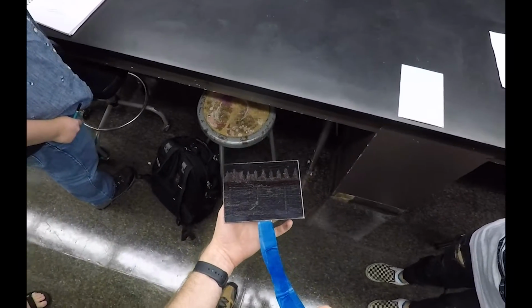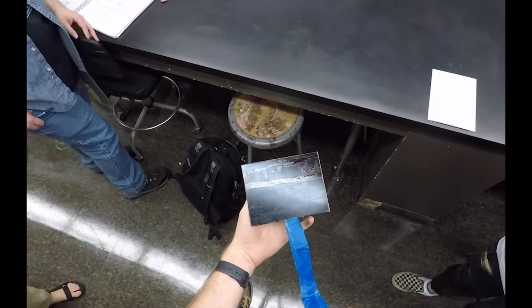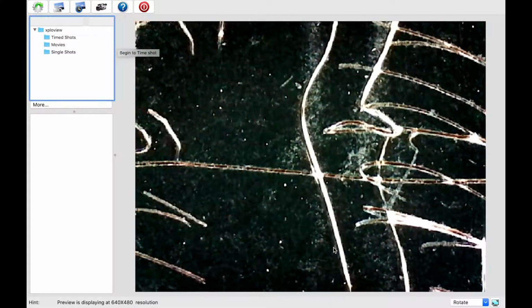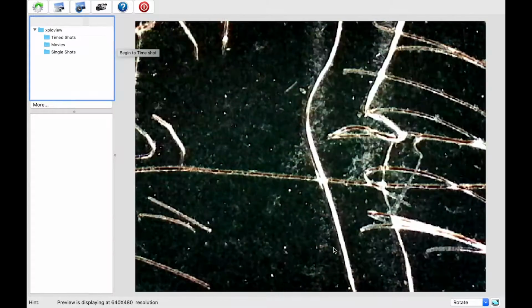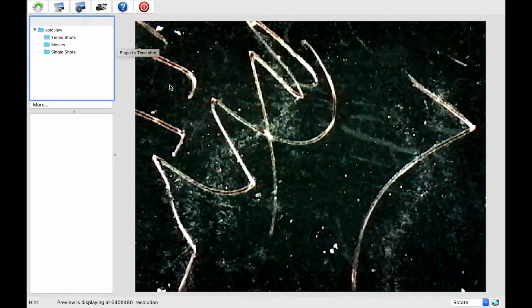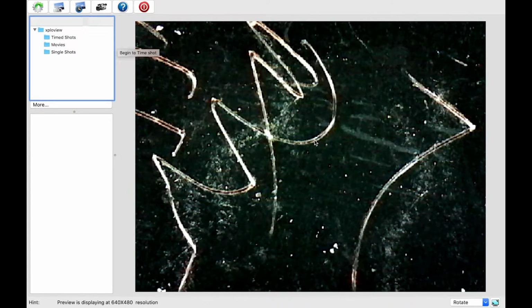Yeah, it's just a lot more clear, right? So let's look at the microscope. I think it's deeper. You can see those little cast shadows are a lot more obvious. All that stuff, deeper. So that's a cumulative 60 minutes. These would be even deeper if we had just put it in and left it for 60, because it takes time for the reaction to start again between the copper and the ferric chloride. When I say cumulative 60, it's less than an actual straight 60. But obviously we can't do straight 60, so.